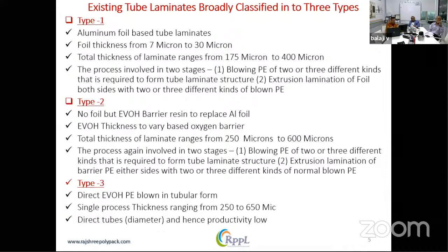Type 2, no foil, but EVOH barrier resin is used instead of foil. EVOH thickness varies to match the oxygen barrier. The thickness ranges from 250 to 600 microns. Here again, the process involves 2 stages. First is blowing of PE, whether it's plain or a barrier, and then extrusion lamination. This is a conventional method of producing.